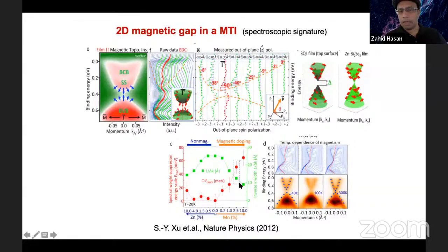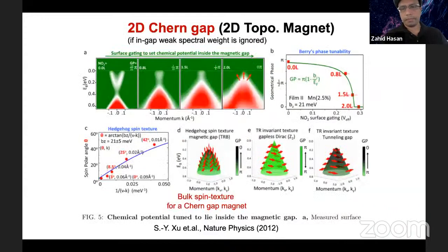If you place the Fermi level here, the Fermi surface is not polarized. We also played with non-magnetic doping versus magnetic doping, to see whether the gap size is increasing with magnetic doping or not. It has its own complication. It also introduces additional disorder, and disorder can change the chemistry of the surface in some unexpected ways. Another thing is that we introduce how to tune the chemical potential. It's like chemical gating under UHV, and see whether we can probe the Berry phase in a spectroscopic way, and whether there's Berry phase tunability.